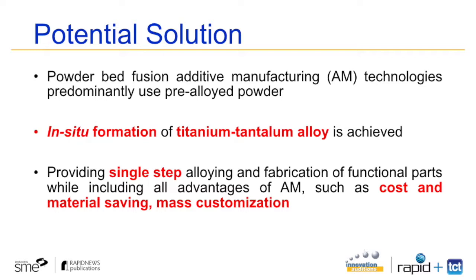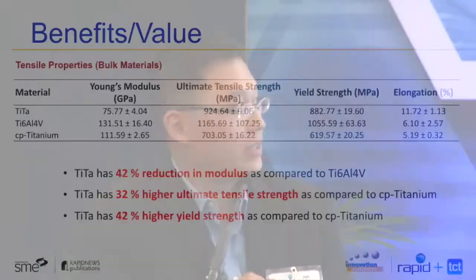Whereas for us, we use powder blends that provide us the opportunity for in situ formation of the alloy as well as the functional parts in one single step. This actually allows us to skip the pre-processing of alloying the material. And how does this benefit us is that we can actually provide homogeneous alloys that are impossible to create because of high melting temperature by conventional methods, and the performance is actually similar to using a pre-alloyed material. This allows us to skip the step while maintaining the mechanical properties.